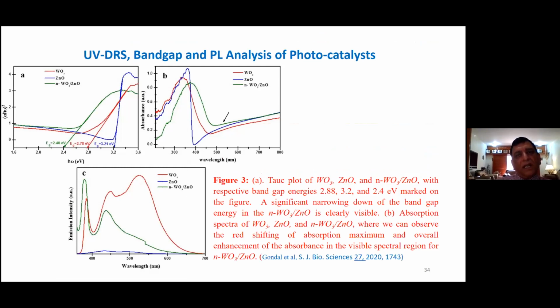The important thing is how we can monitor whether the electron, which is excited to the conduction band, jumps back to the valence band. And that we can do very easily with photoluminescence analysis. If the emitted light is more, that means electron-hole recombination is taking place. And that is clearly seen here: for pure WO3, in red, there is a lot of emission, a high photoluminescence emission intensity.